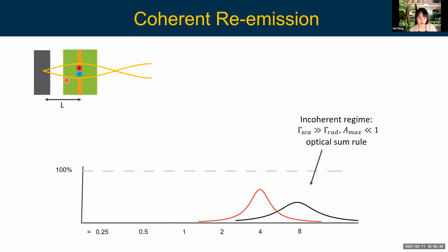And when you do that, which is also typically what you deal with when you don't put materials into a high quality cavity, what you will see when you send light to it and look at the reflection or transmission is some absorption. The absorption will be very tiny, typically less than a few percent, and it has a certain height and width. The area underneath is conserved.